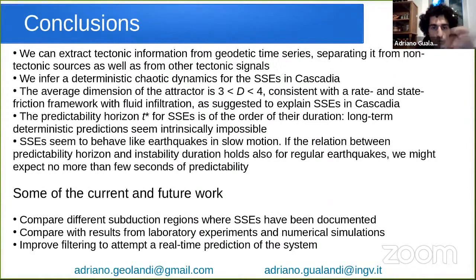So to conclude and try to summarize all these points, a good thing is that we can extract the tectonic part of the information from the geodetic time series, which contain continuously, basically, the information on the slip on the fault, and not only a point process. Then we can infer something about the dynamics of the system, and we found that it is consistent with deterministic chaotic dynamics for the slow events in Cascadia, with an average dimension of the attractor of the order between 3 and 4. That is consistent with a rate and state spring slider with fluid infiltration.